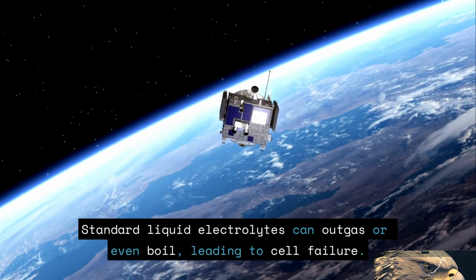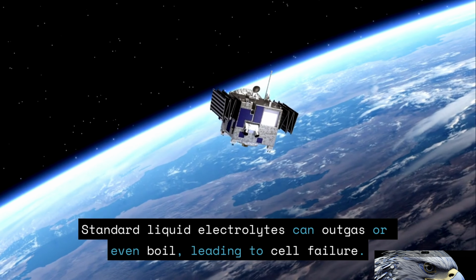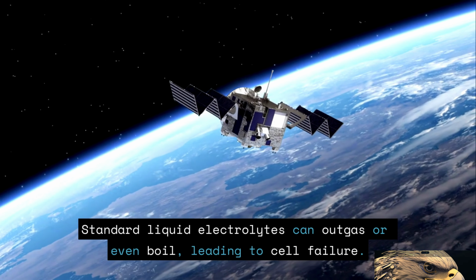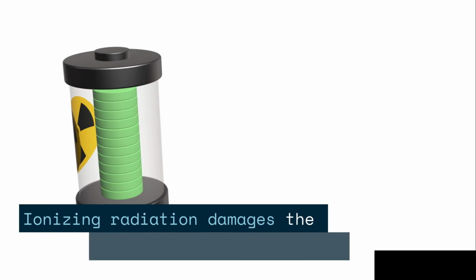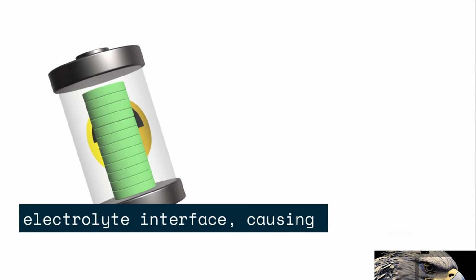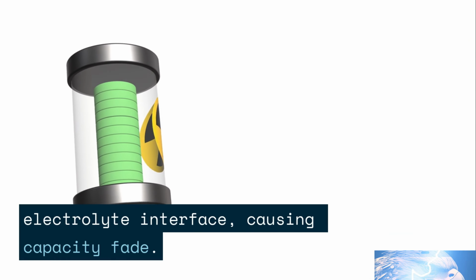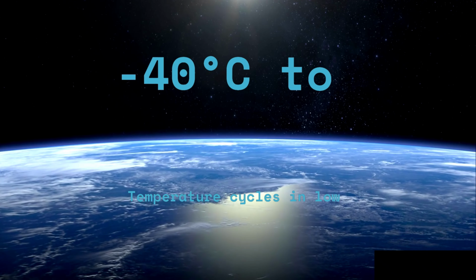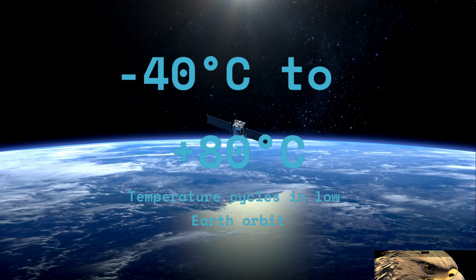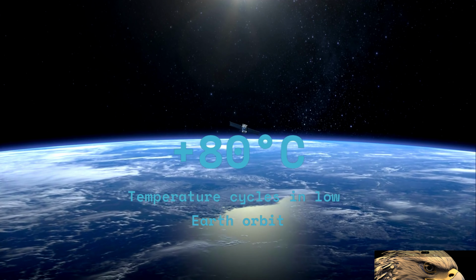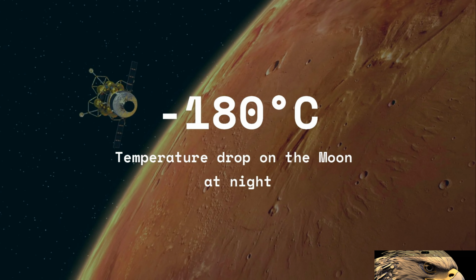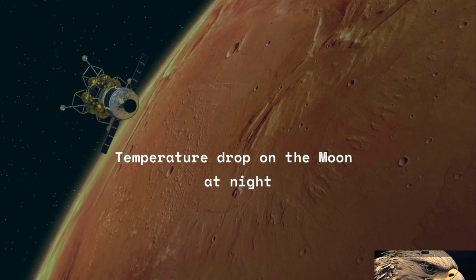Standard liquid electrolytes can outgas or even boil, leading to cell failure. Ionizing radiation damages the electrolyte and the solid electrolyte interface, causing capacity fade. In low Earth orbit, temperatures cycle between -40 degrees Celsius and plus 80 degrees Celsius. On the Moon, it drops to -180 degrees Celsius at night.